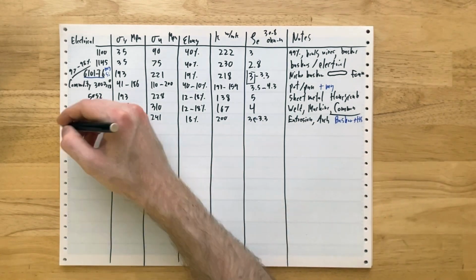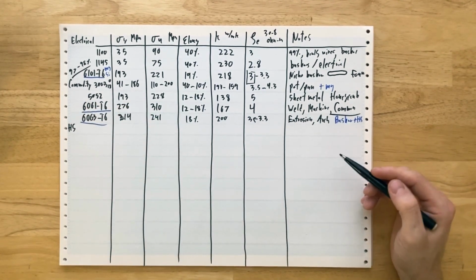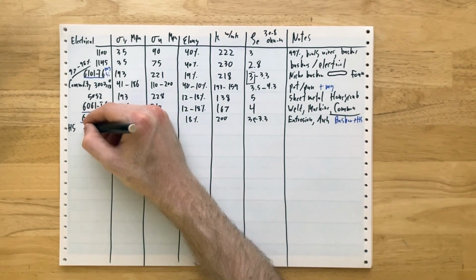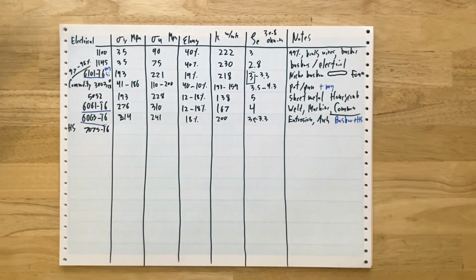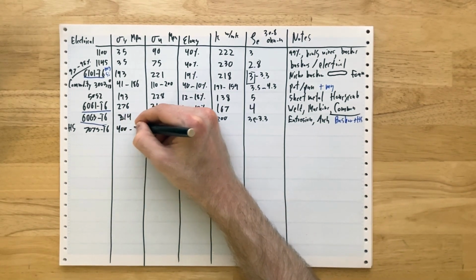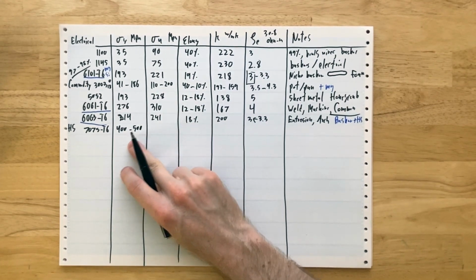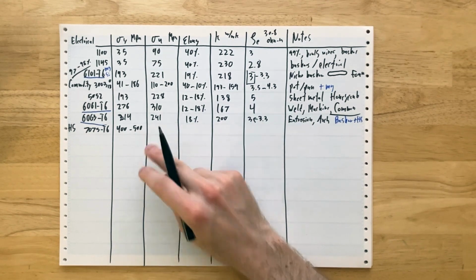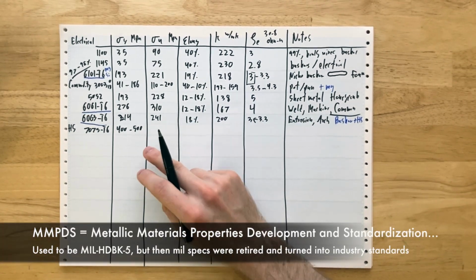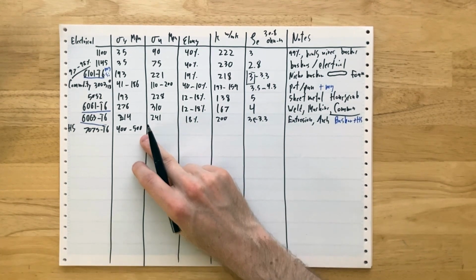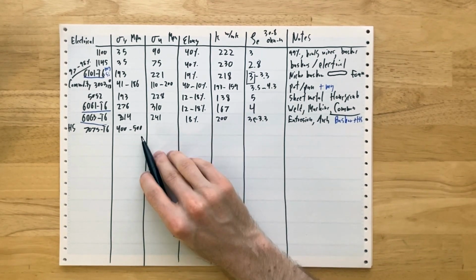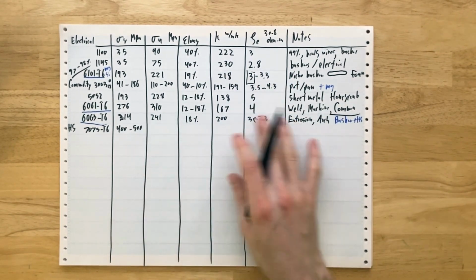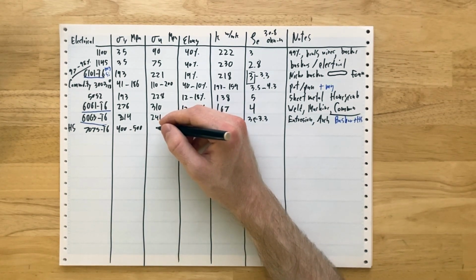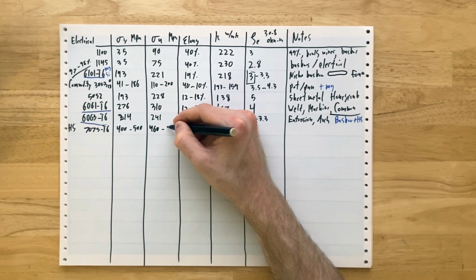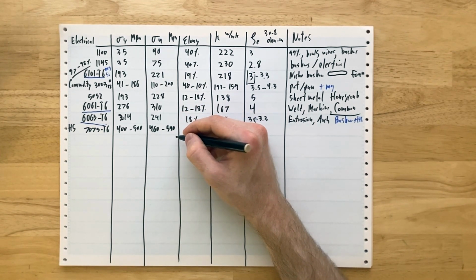Okay, now we're getting to the high strength materials. So this is what I would actually call an aerospace grade aluminum, something that's used for its high strength. That is, of course, 7075 T6. This is your most common high strength aluminum alloy. You can still get it really available almost anywhere. Yield strength, 400 to 500 megapascals. Really high. I'm putting in a range there because it's thickness dependent. This is a material people have studied in depth. If you go to MMPDS, the Metallic Materials Properties datasheet, or Mil Handbook 5, which it was based on, you'll see that for thin sections, you get higher strength. For thick sections, like 4 inches thick, strength goes down. Make sure you look that up, but basically high strength. And the ultimate is also fabulous, 460 to about 540. Also thickness dependent.